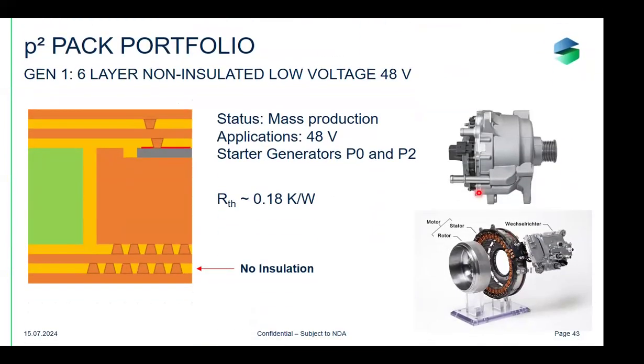Why did we have these different kinds of applications? As pointed out, in the first generation, there was no need for an insulation, because this is maintained with a thermal insulating material, but these two layers of copper-filled vias are used to reduce the thermal resistance from the component to the outside to a very low value. So it's in the area of 0.2 kelvins per watt. If you have several components, this must be divided by the number of components, but per individual cell, you have 0.2 kelvins per watt.